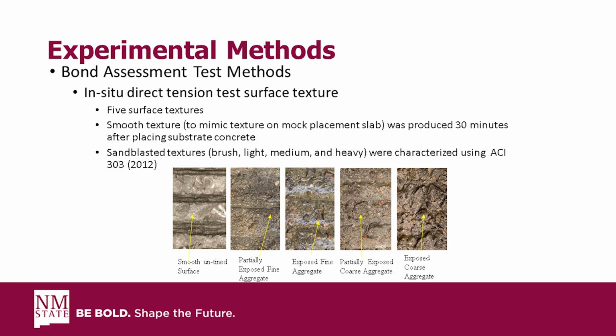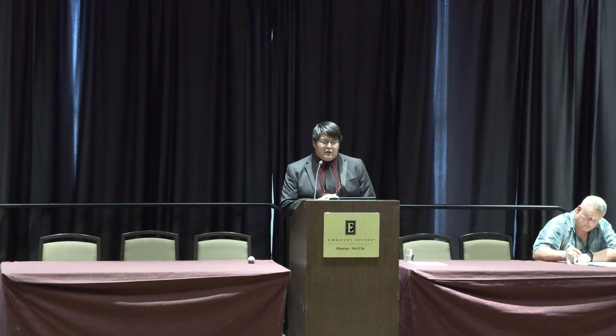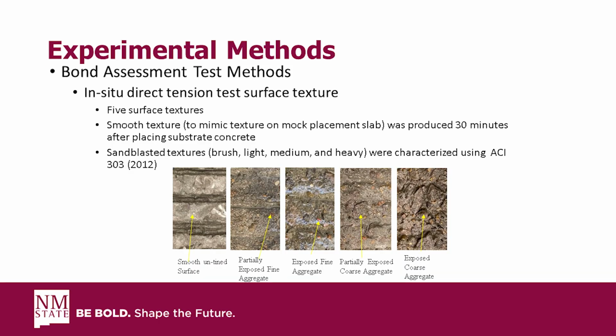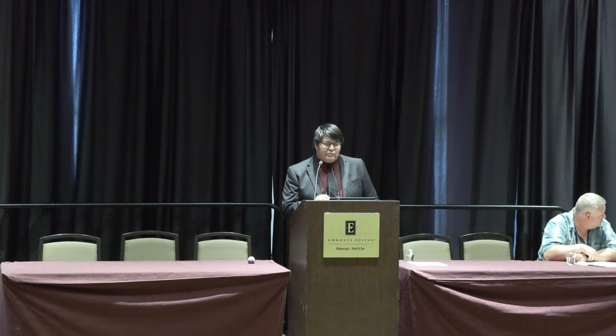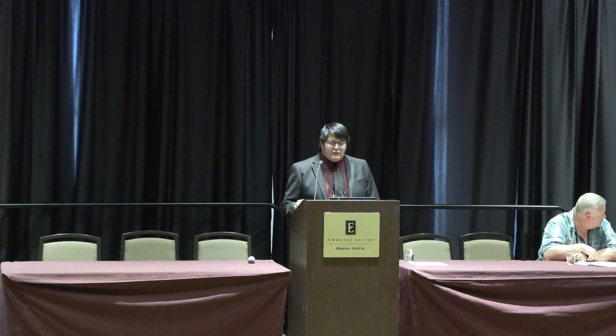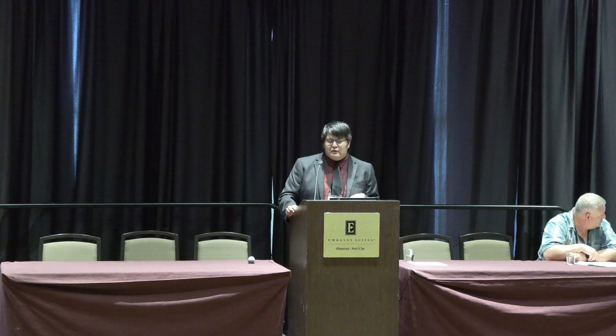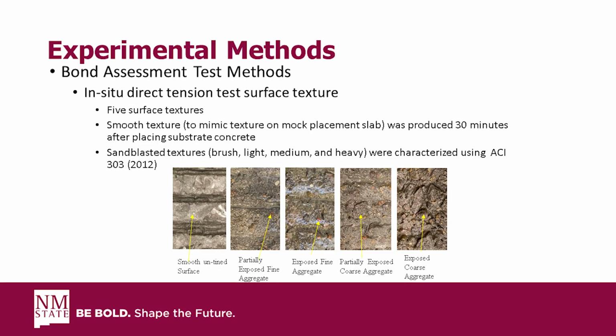So what we're looking at mainly is that top surface, which is the smooth, or as we go into this other texturing. We define the next textures as exposed aggregate, but more importantly than exposing aggregate is exposing the pore space of those aggregates. We defined these substrate surface textures as sandblasted textures, defined by ACI 303's definition of brush sandblast texture, which is the second image on the screen here.